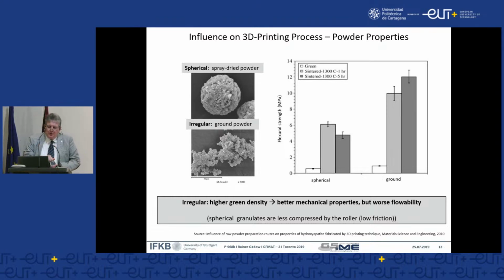But if we use this additional attrition milling operation, that means we have a much better homogeneity in the suspension. We can nearly double the strength. And here also the longer sintering time is beneficial, so that we obtain a material with a flexural strength up to 12 megapascal. Typically the desired value is around 10 megapascals, so that this goal could mostly be achieved.